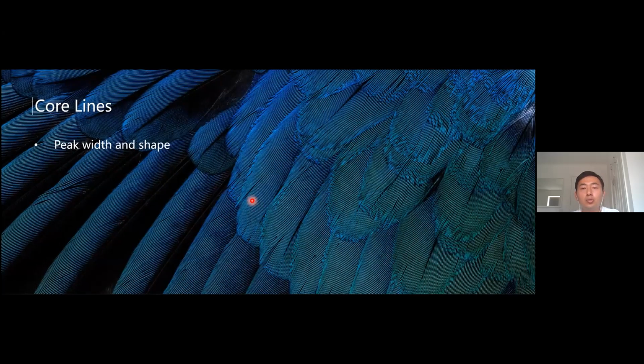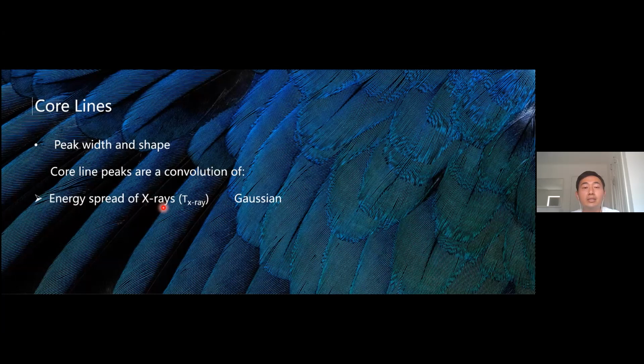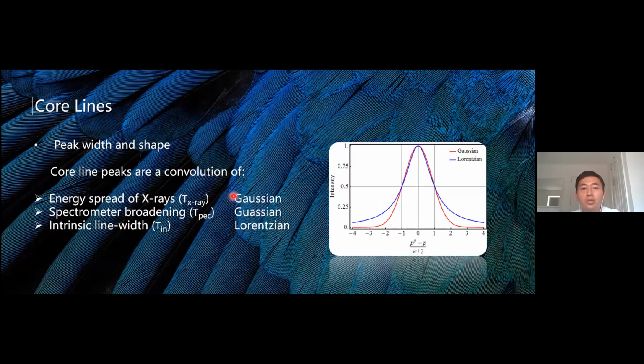Once we know where the peaks should be, we will need to identify the peak width and shape. The peak is a convolution of the energy spread of X-rays, the spectrometer broadening, and the intrinsic line width, which is due to the lifetime of the photoelectrons. The first two are Gaussian shape.